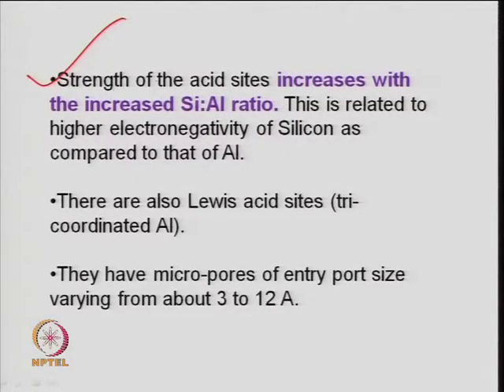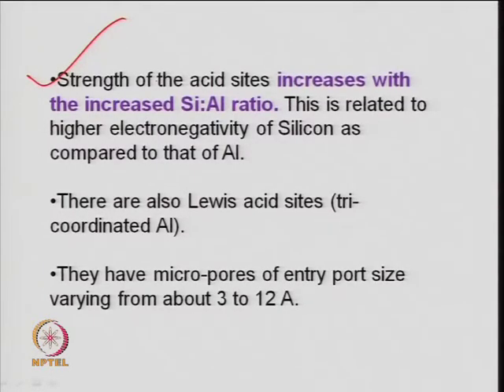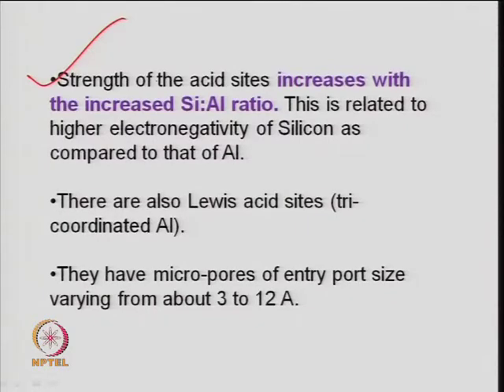A certain concentration of silicon-to-aluminum is required to match desired reaction activity. The number of acid sites is important, but the strength of the acid — whether Brønsted or Lewis, stronger or weaker — is also important. This can be characterized by ammonia TPD or IR spectroscopy with pyridine to identify Brønsted-type and Lewis-type acidity.